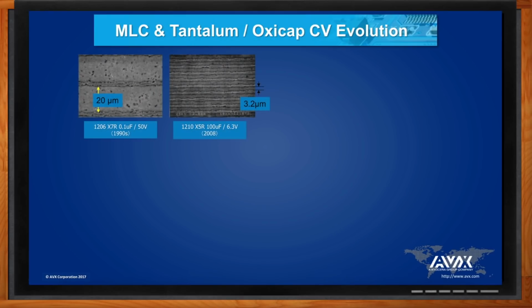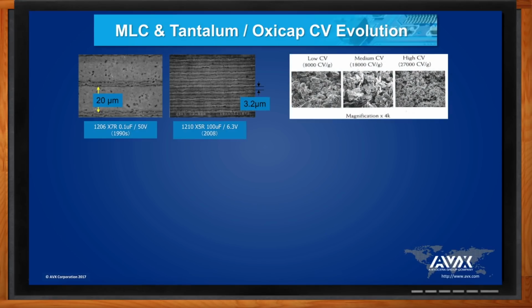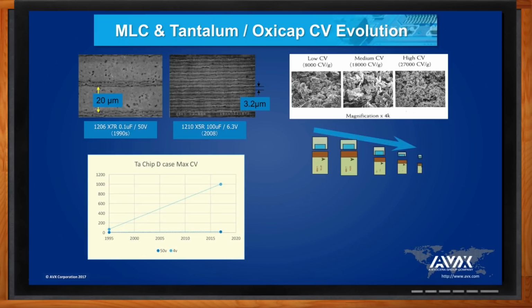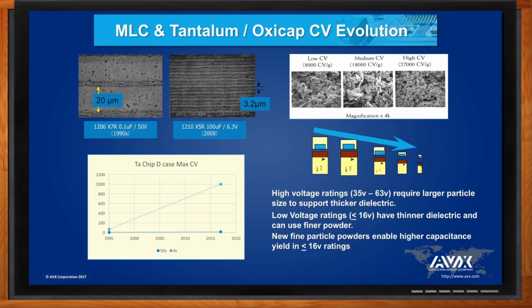And if we go and look at this comparison here, just a cross-section of the ceramic, see how we're making these very thin slurry-type layers now down to the micron level. We're really significantly increasing the capacitance. And these are very low voltage devices, 4 to 6 volts. Now we do the same in tantalum. As tantalum powder technology has evolved, we've been able to use finer and finer grain tantalum. And if we sinter this into a block and have very, very thin dielectrics, then we can have a huge surface area and increase capacitance from the thinner dielectric. So again, 6 volts and 4 volts are taking advantage of really high surface area powders.